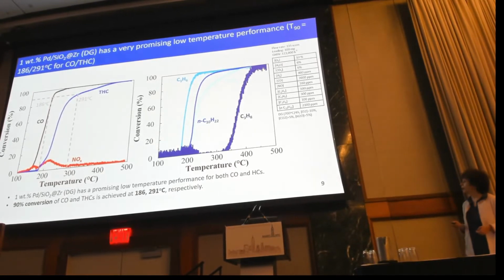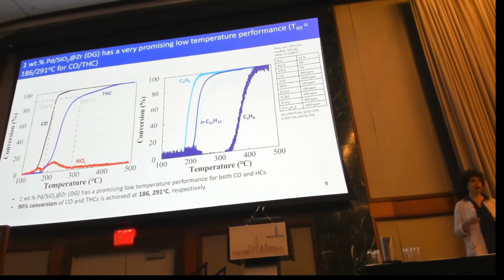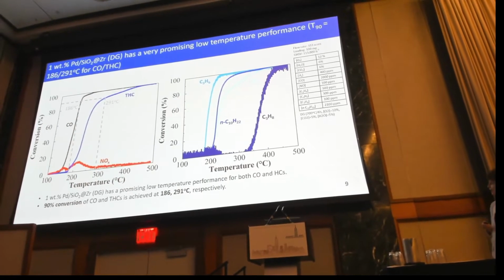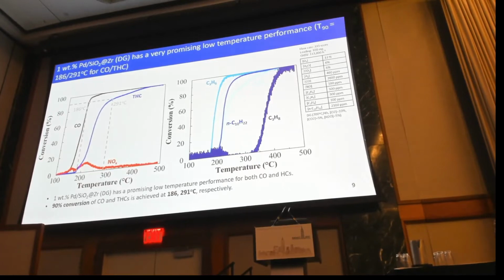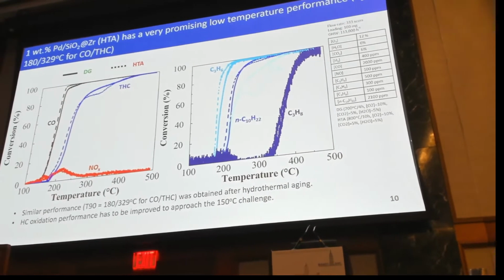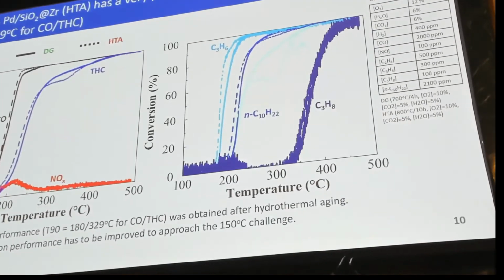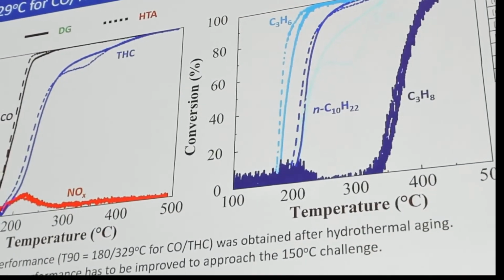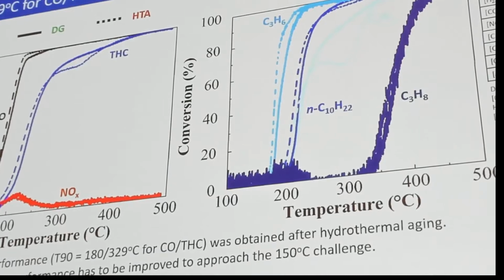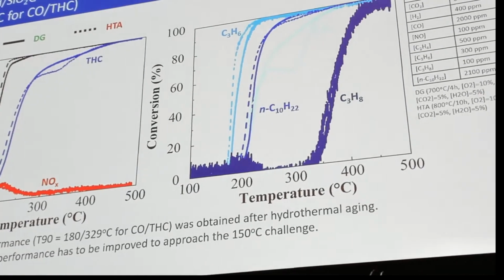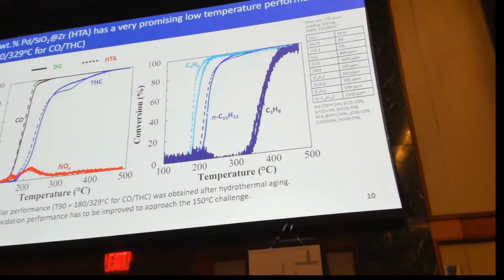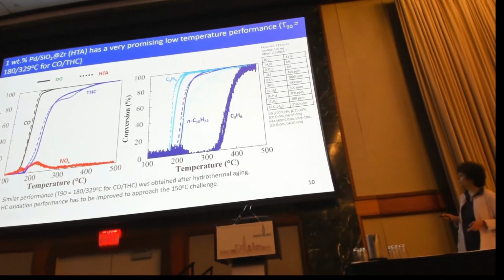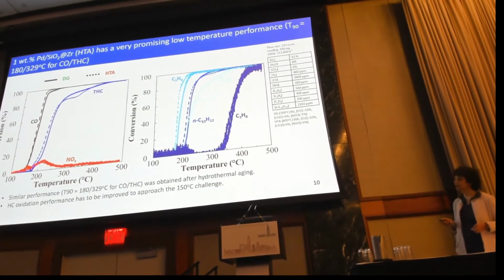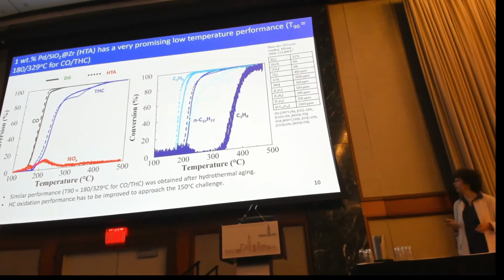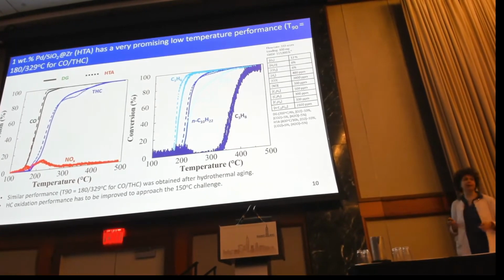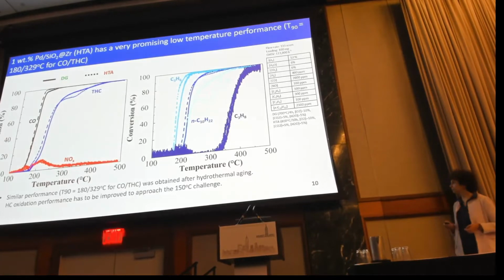Okay, but of course at the beginning we want to see the hydrothermally aged performance. So we hydrothermally age the catalyst at 800 degrees C for 10 hours. And here you can see the data after aging, which is the dashed lines here. What is interesting to notice is that usually we expect after aging that the catalyst is going to be deactivated. But what we see here is that actually the catalyst is able to maintain its performance after aging. So we don't see a major difference before and after hydrothermal aging. That shows basically that the catalyst is thermally stable.